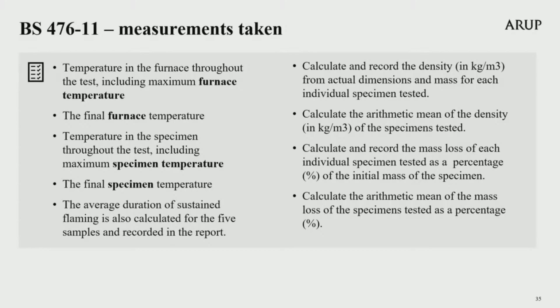The operator is also required to calculate and record the density, calculate the arithmetic mean of the density, calculate and record the mass loss of each individual specimen, and calculate the arithmetic mean of the mass loss of the specimens tested as a percentage. These 5 measurements must be recorded in the fire test report.